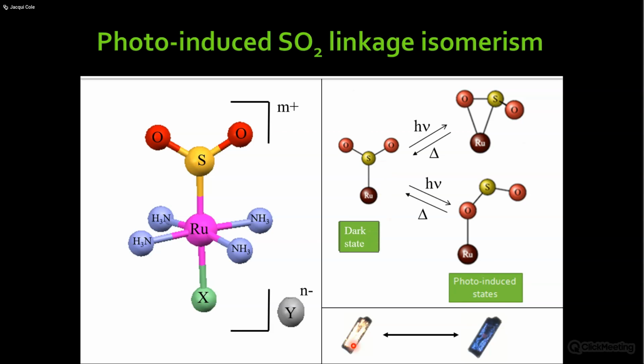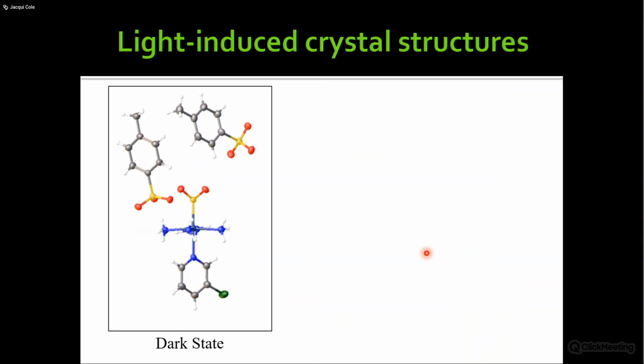dark state, for example. And what you see in terms of the physical manifestation of the crystal is generally that you'll have some photochromic effect. So the crystals will change color, particularly when you're moving from this dark state into the oxygen-bound ruthenium photo-induced state. So that's the nature of the system. So that's the switching part. And I'll go through now the sort of mechanism that we typically see in this series of complexes. And as I say, where we change the trans ligand, so that's the ligand here.